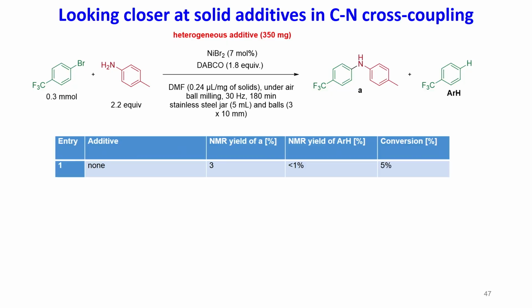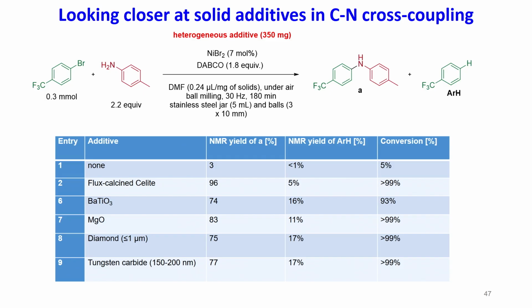So we looked at this reaction more closely. For example, what happens if you don't have an additive? We just mix the reagents and ball mill them. Well, it's not very efficient, the yield is extremely low. Now, if we add Celite, the yield goes up dramatically, extremely efficient. But it's not just Celite. We can also see an increase of the yield with barium titanate, a piezoelectric material, with magnesium oxide, a non-piezoelectric material. We can even use diamond powder, and we can use tungsten carbide. And actually, there is nothing in common between all of these materials. And it's very unlikely that they may act as a strong enough reductant, with some exceptions, for the nickel catalyst. So what's actually going on in this reaction?